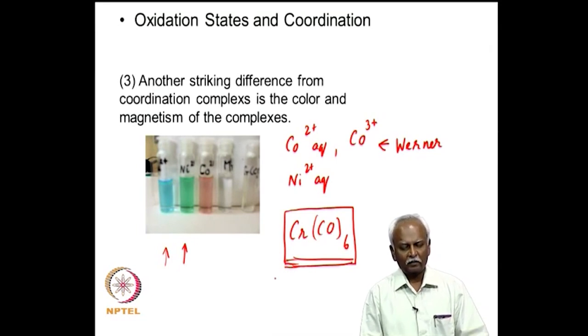So, this is also to be noted, the fact that magnetic properties of the Werner complexes are often either diamagnetic or paramagnetic. They tend to vary. It depends on the oxidation state. It tends to depend on the strength of the ligand. If you have very strong ligands, they tend to form low spin complexes or even diamagnetic complexes if the electron count is right. Whereas, in the case of organometallic complexes, almost all of them tend to be diamagnetic.